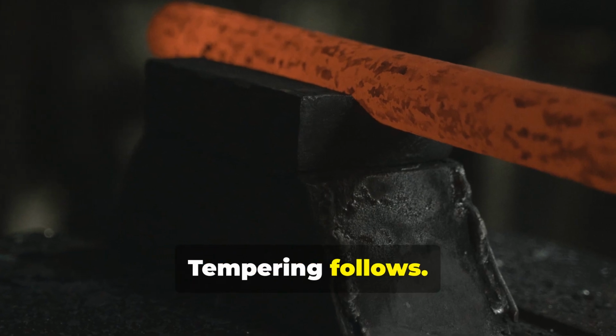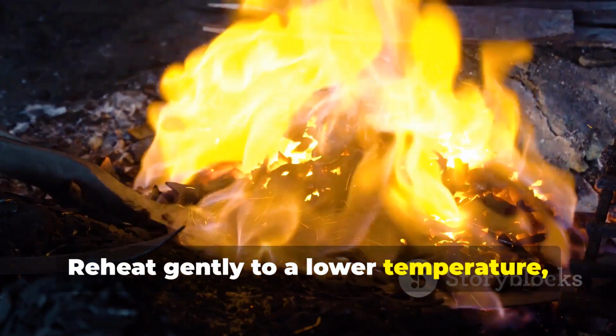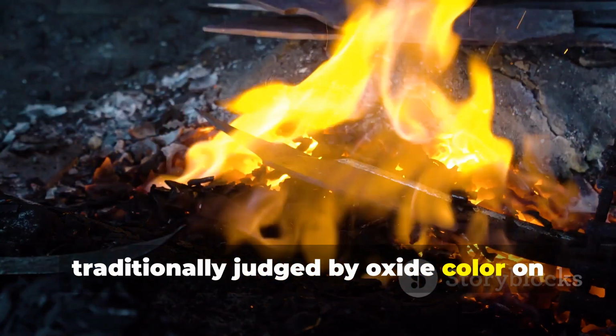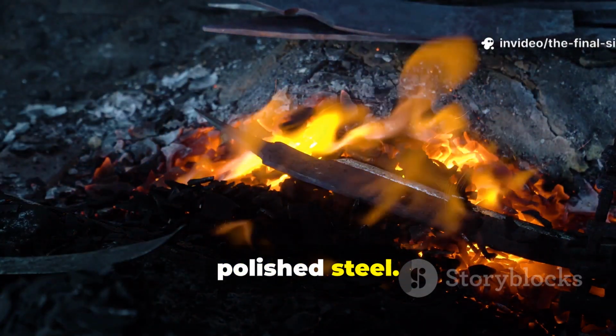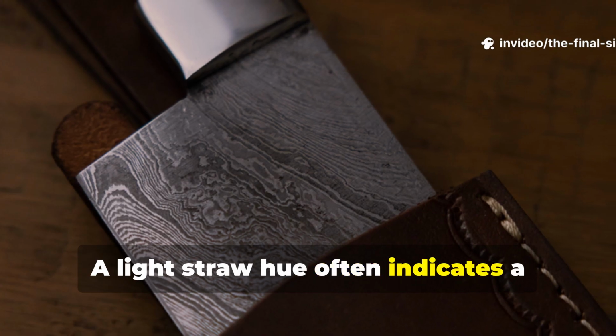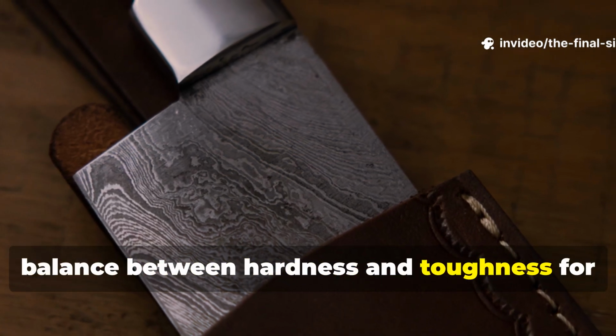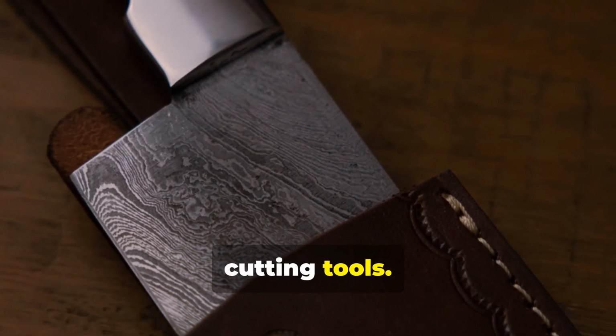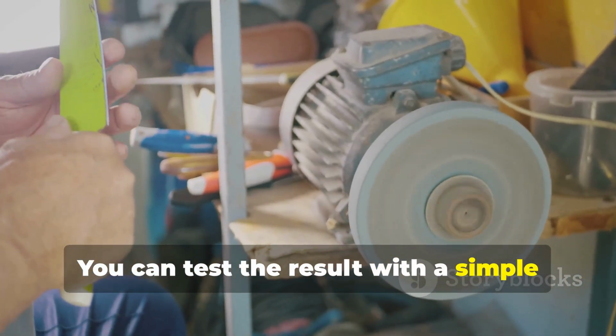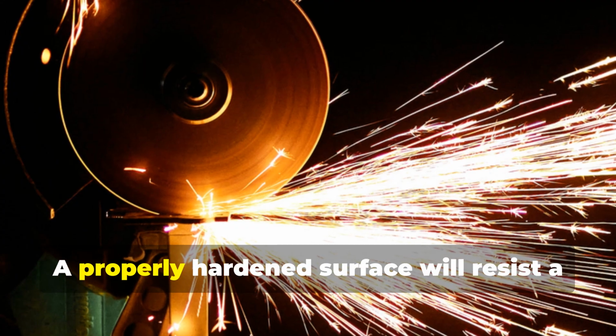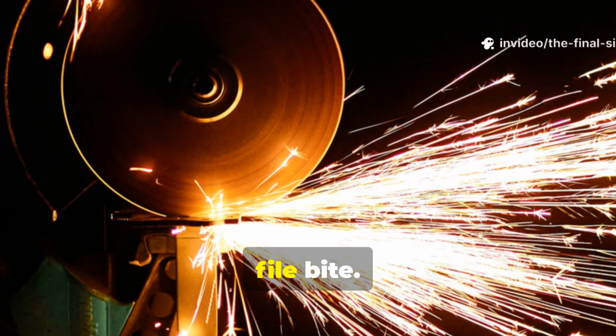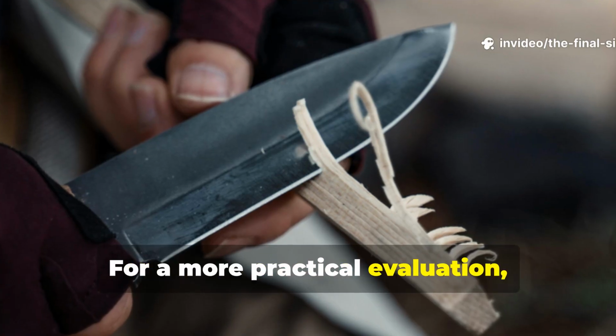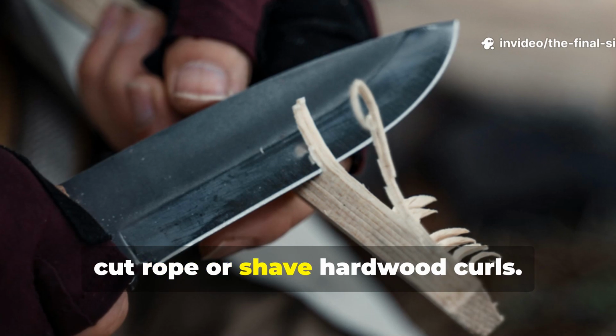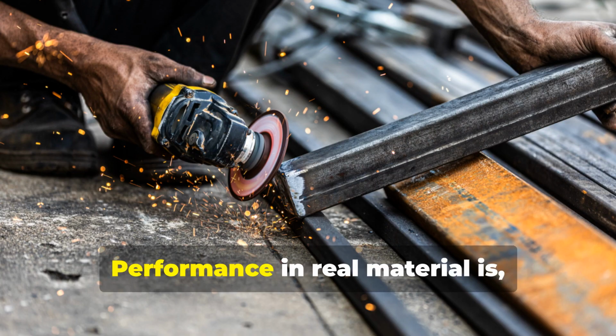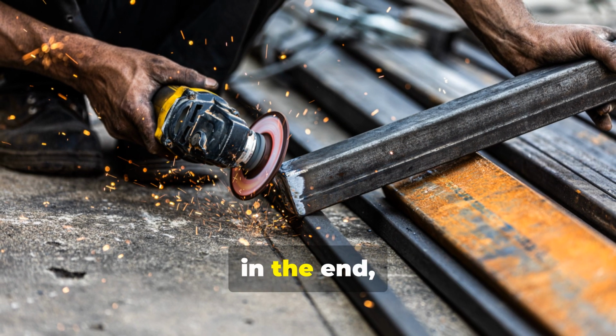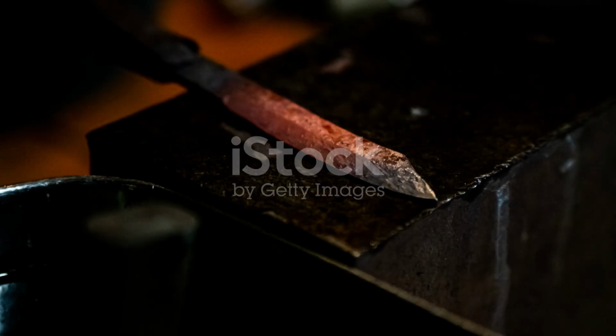Tempering follows. Reheat gently to a lower temperature, traditionally judged by oxide color on polished steel. A light straw hue often indicates a balance between hardness and toughness for cutting tools. You can test the result with a simple file test. A properly hardened surface will resist a file bite. For a more practical evaluation, cut rope or shave hardwood curls. Performance in real material is in the end the ultimate measure.